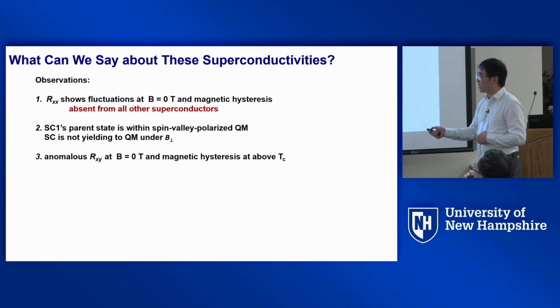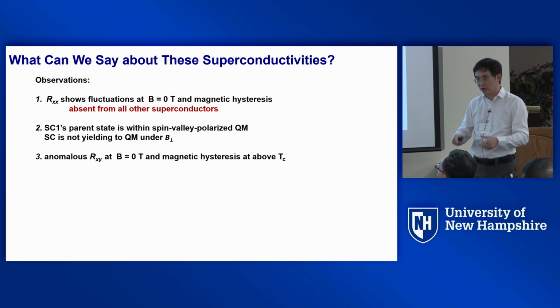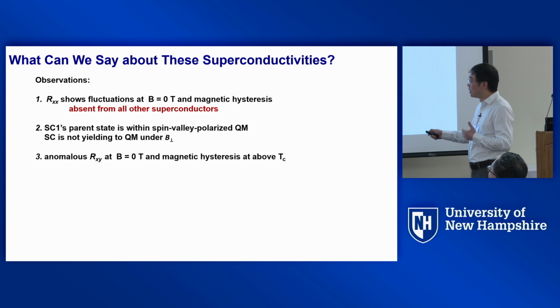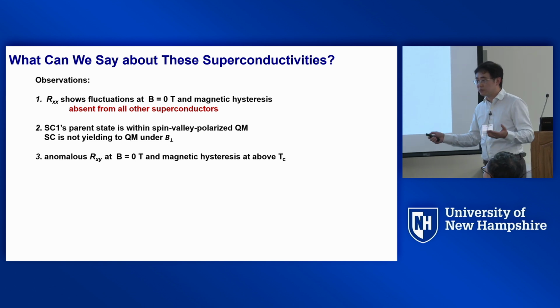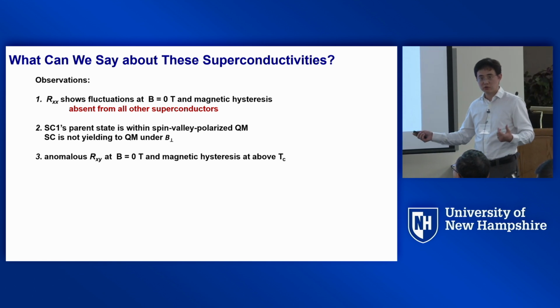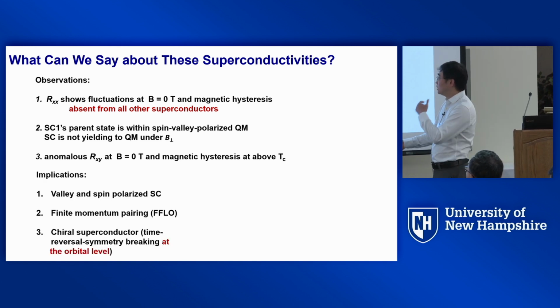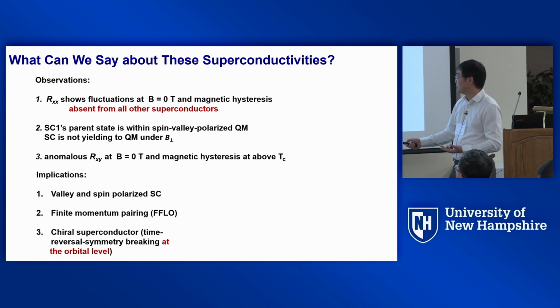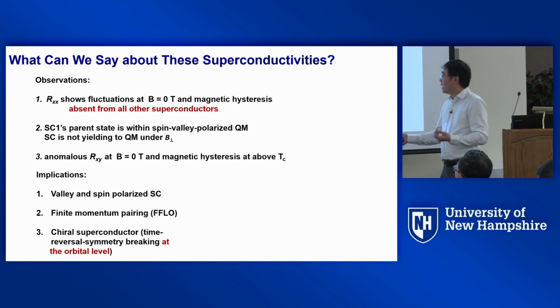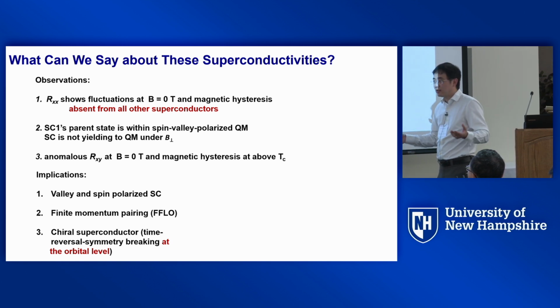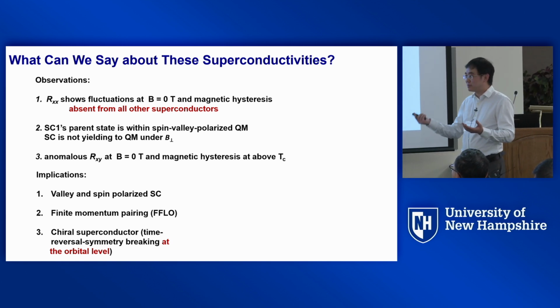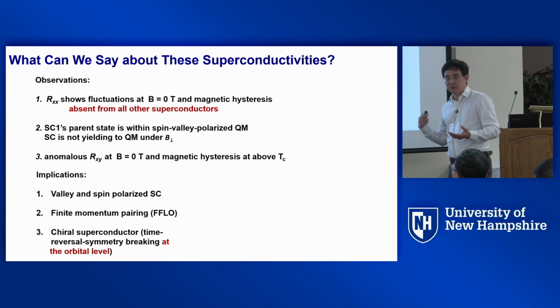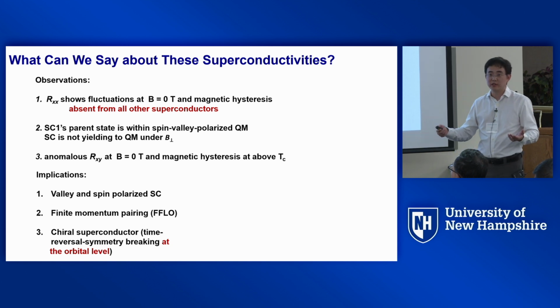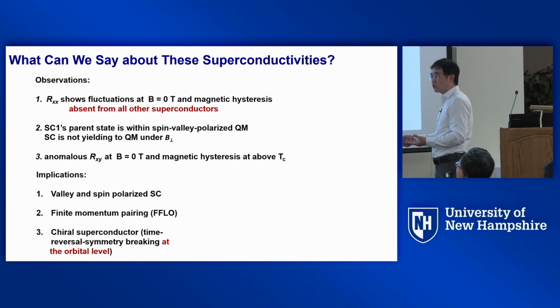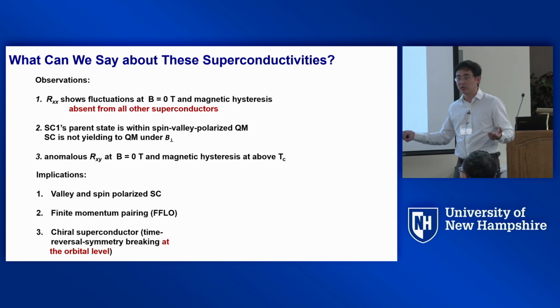These are the observations. Okay, you get the magnetic hysteresis in the superconducting state below TC. You get anomalous Hall hysteresis above TC. And these are just unique observations of this superconductor compared to other superconductors. And if you believe this is a spin valley polarized parent state, then it has to be finite momentum pairing, right? And it has to be chiral because it breaks time reversal symmetry, not just by the spin, but the valley, the orbital motion breaks time reversal symmetry. So time reversal symmetry is broken at the orbital level, and this distinguishes it from the so-called ferromagnetic superconductors people find in heavy fermion systems.